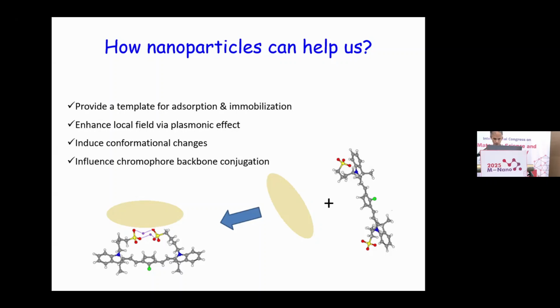Then nanoparticles, if they have free electrons, can produce a plasmonic effect, which can also enhance photoluminescence by the local electric field. Also, nanoparticles can induce conformational change of the molecules. When molecules adsorb on the surface of the nanoparticles, they can change conformation, and if this conformation is favorable for photoluminescence, then we can observe a higher quantum yield of photoluminescence. And also, as a result of adsorption, we can induce improved conjugation of the chromophore.